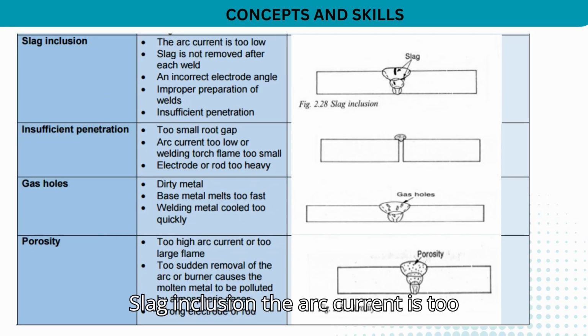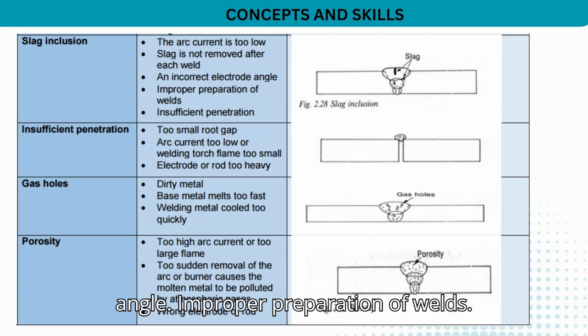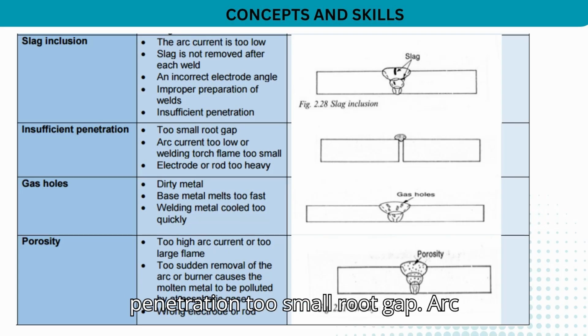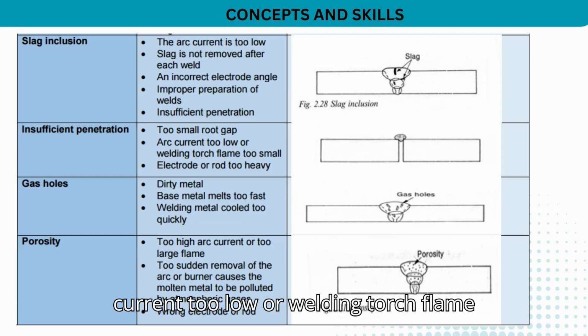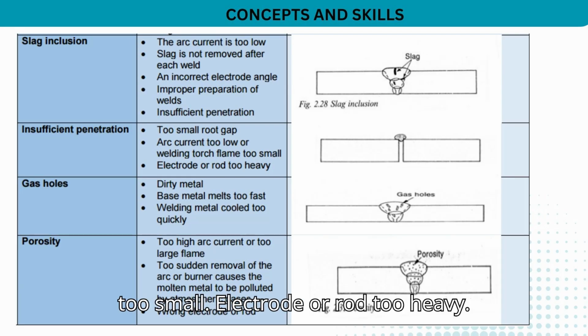Slag inclusion: the arc current is too low. Slag is not removed after each weld. An incorrect electrode angle. Improper preparation of welds. Insufficient penetration: too small root gap. Arc current too low or welding torch flame too small. Electrode or rod too heavy.